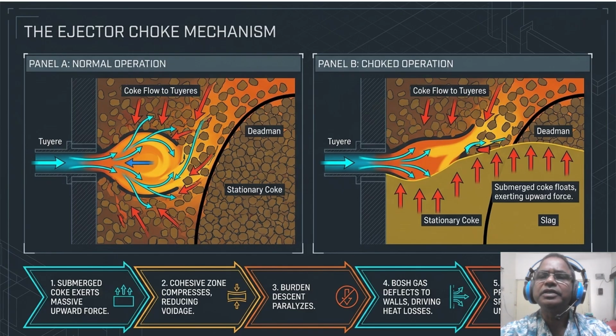So what it results in is massive. It has a cascading failure. Bosh gas can no longer move through the center, so it deflects to the wall, driving extreme heat losses and causing blast pressure to spike uncontrollably. So you are not just losing production, you are destabilizing the entire structural integrity of the blast furnace. This mechanical paralysis is why dry hearth casting is not a suggestion, it's a thermodynamic necessity to maintain a stable blast furnace and consistent burden descent.